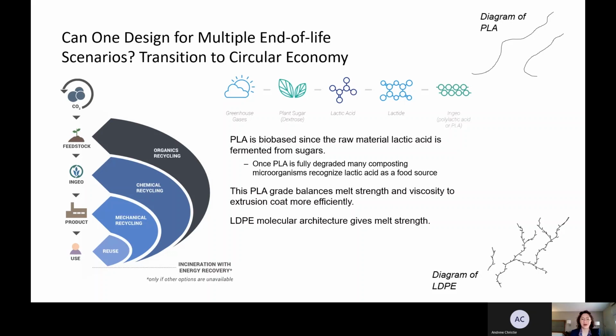So, the coated paper cup normally is coated with low density polyethylene, and that has a molecular architecture that gives it melt strength. You can see a diagram in the bottom right there. This is what all of our existing equipment has been designed for, and it has, like I said, great melt strength. PLA, you can see the diagram of PLA in the upper right, is a lot different. And so we've done what we can to increase that melt strength and viscosity in this PLA grade that we studied. It balances those two, melt strength and viscosity, to help with the extrusion coating. And beyond just looking at resin, you also need to consider the equipment. So now Andrea will take us through the extrusion coating process.